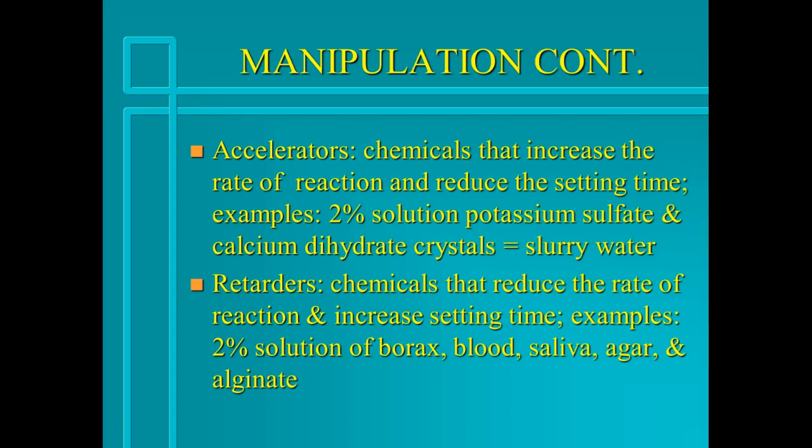Retarders are chemicals that reduce the rate of reaction and increase setting time. Examples of retarders are 2% solution of borax, blood, saliva, agar, and alginate.